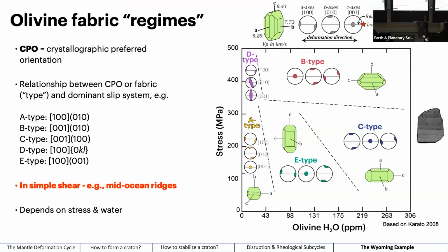That would be active. And olivine is great because there's been lots of experiments. It's orthorhombic. We can understand it. There's only so many ways it can deform. So there's been a lot of experiments that have, for instance, parametrized the amount of water that's dissolved in olivine as a function of stress. And different types of olivine crystallographic preferred orientations or fabrics evolve with different water contents and stresses. And so we can get all these different types of fabrics that correspond to different slip systems in olivine. So that can tell us something about the geodynamic state of deformation.